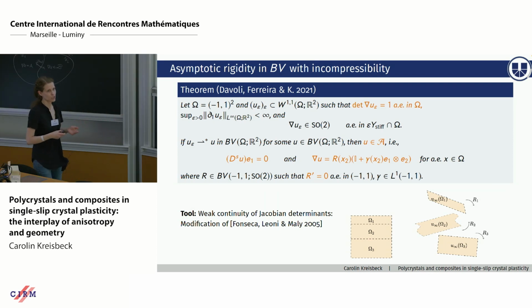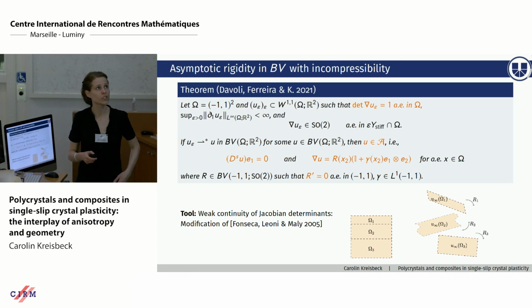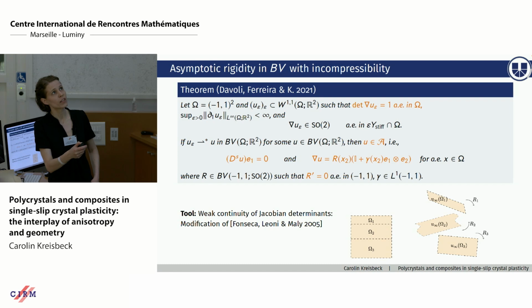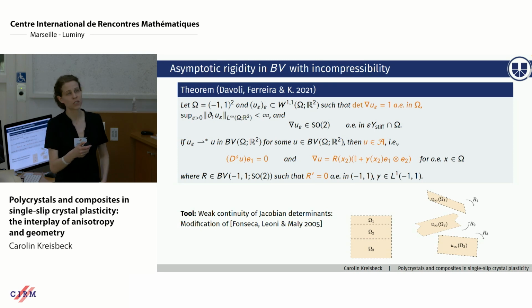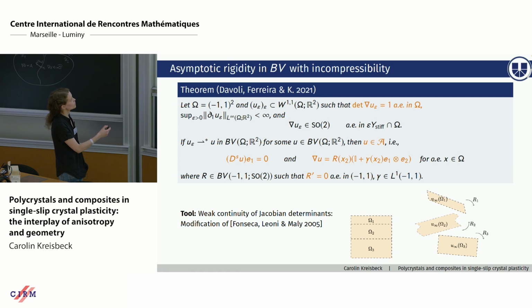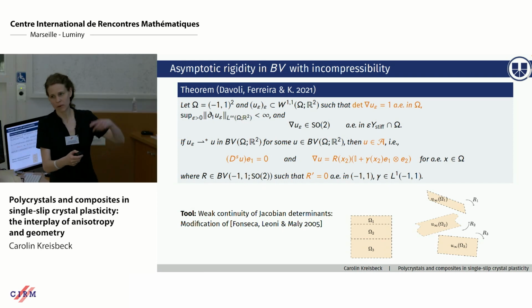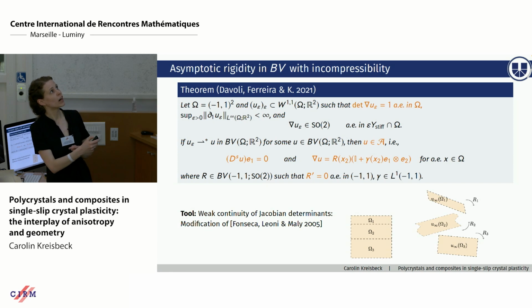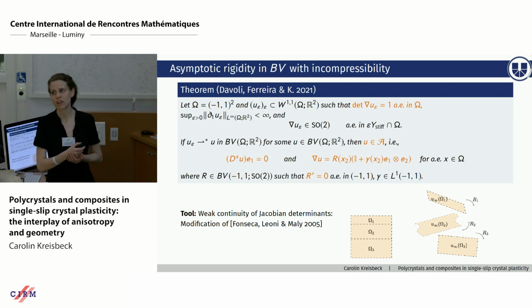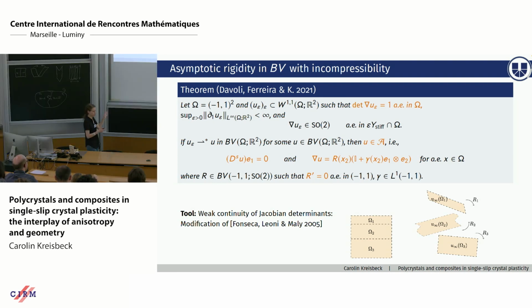If we have that, we can use weak continuity results of the Jacobian determinant and derive that our limit deformation really lies in the set A, which is characterized by these two expressions here. So what do they say? The first one is the absolutely continuous part with respect to the Lebesgue measure. This looks almost like the gradients that we had seen in the case P equal 2, but now R is a BV function that has vanishing absolutely continuous part. On the other hand, for the singular part, we see that it vanishes in the E1 direction.